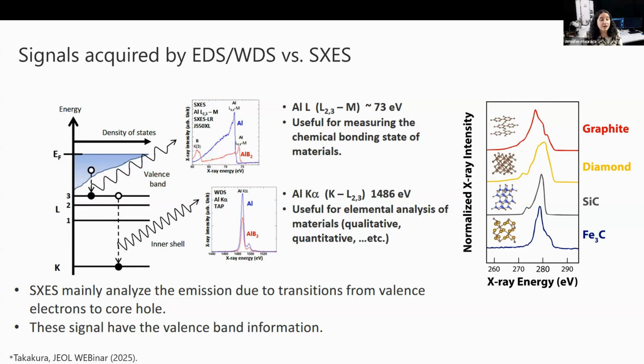So what this novel technology translates to, besides detection of low energy elements like lithium, is the ability to assess the chemical state information, such as shown in the graph on the right, where the asymmetry and peak width in the carbon K line directly relate to the p symmetry of the carbon valence bands. So with SXES, we can tell the difference between graphite and diamond, even though they are both completely made of carbon, something that's not possible with EDS or WDS.